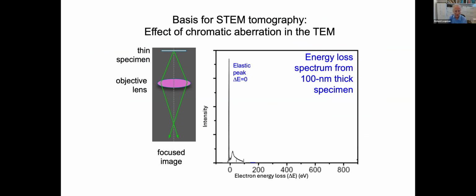Now, just very quickly, the basis for STEM tomography. Why do STEM? Well, in the TEM, when you're looking at a thin specimen, most of the electrons go right through the sample, and there's very little inelastic scattering. That's shown here in the energy loss spectrum. There's some amount of inelastic scattering, but not an awful lot. So everything is focused for a thin specimen. The image is focused in the TEM.